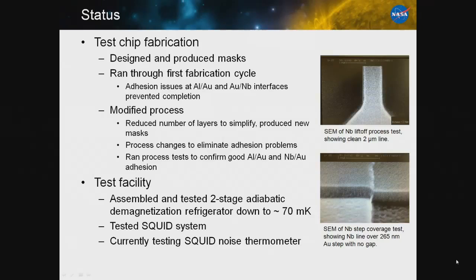We've designed and produced the masks. We've run through our first fab cycle last year. We ran into some adhesion problems, different particular adhesion problems, one at the aluminum gold interface, another at the gold niobium interface. And that prevented us from completing last year.